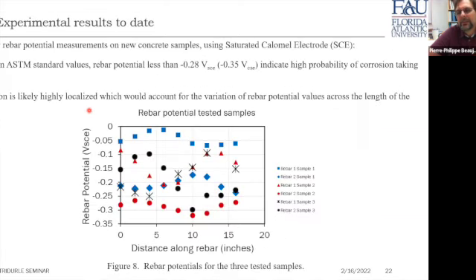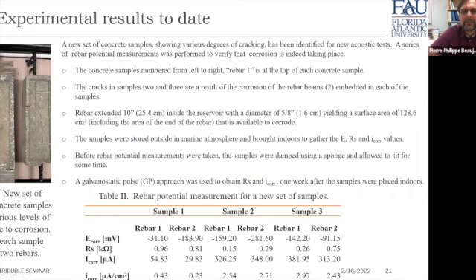What I want to get out of this is that those 3 samples, according to the potential measurements, clearly indicate that we have gradual increase in the corrosion in the rebar, which would indicate that these 3 samples would be good candidates to actually look at the difference in signature when it comes to corroded rebar versus non-corroded rebar using ultrasonic testing.